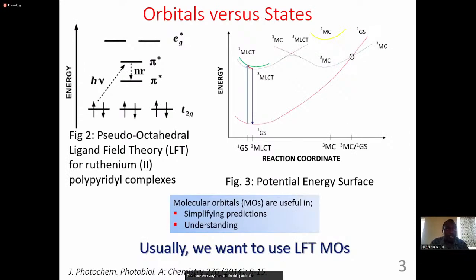There are two ways to explain this particular excitation. The first one is based on orbitals, and the other one is based on states. On the left of your screen is the octahedral ligand field theory, whereby in the splitting you get T2g orbitals and the Eg* orbitals. There's some mixing in between here. You can understand that splitting in this way, or you can understand it using the potential energy surface, whereby there's excitation from the ground state to the singlet metal ligand charge transfer. There's intersystem crossing to triplet metal ligand charge transfer. This can fluoresce back to the ground state, which is very fast. This work is based on the idea that there's a barrier here that needs to be crossed. There's an avoided crossing here. This particular barrier is responsible for the long excited state lifetime, and this is what we shall be looking at.